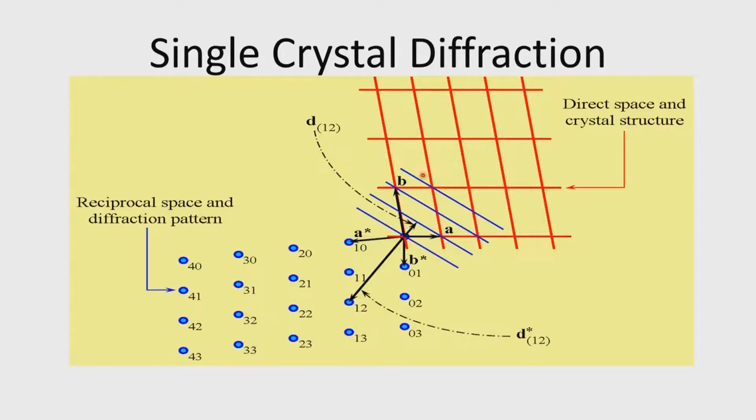So, the atoms are all lying here in this part of the diagram. They are here, here, here, wherever, depending upon where the atom wants to be and where the molecular structure develops or the ionic structure develops and so on. The atoms are connected to each other, as we discussed yesterday. The scattering is done basically by the atoms, that means the electrons associated with the atoms. So, X-rays, when they fall on this crystal, will be diffracted based on where the electron density is found. So, the larger the electron density, the more intense will be the diffracted spot.